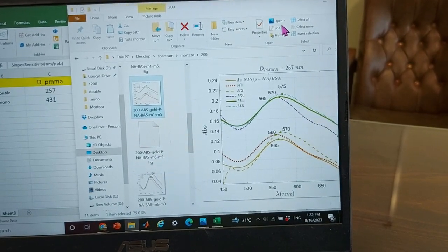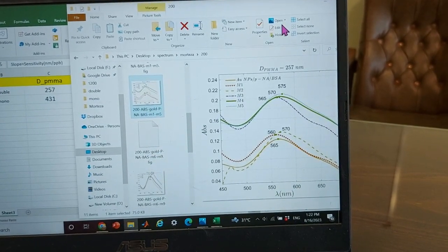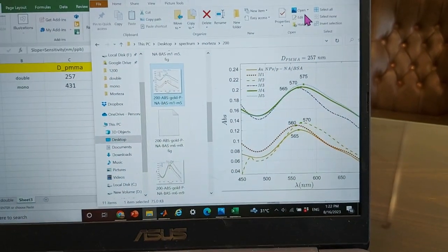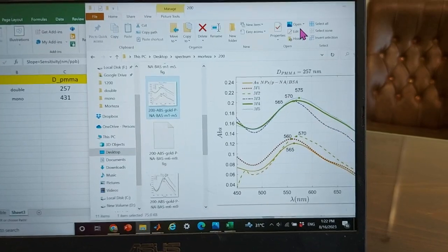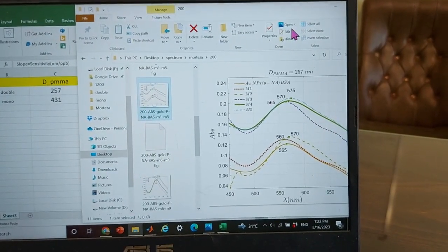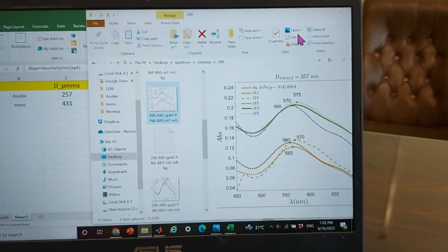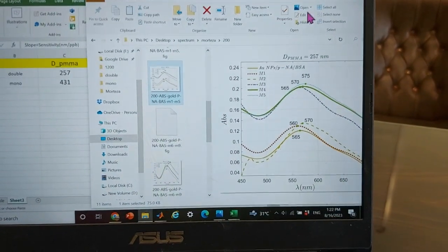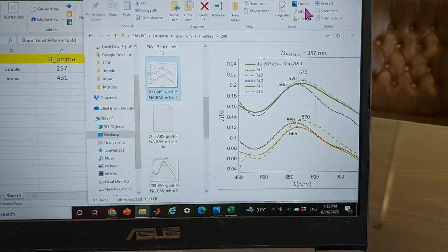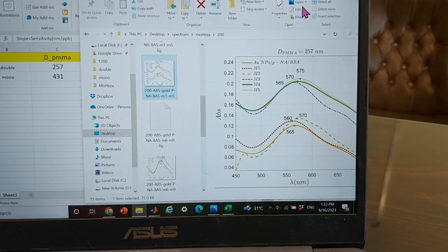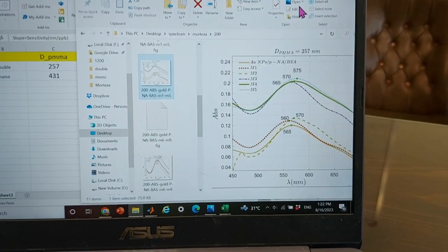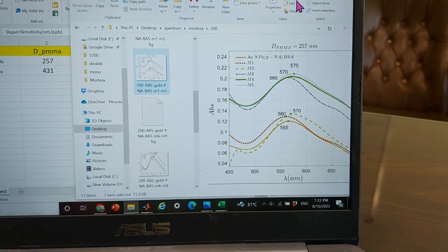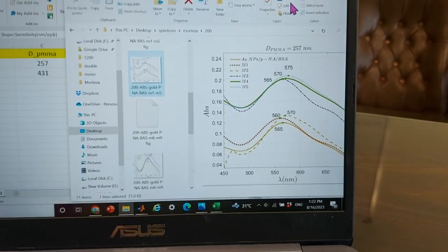But in one layer, you have nanoparticles that are near to each other. So the conclusion of both of your works is saying something very important: whenever we want to fabricate a very highly sensitive LSPR sensor, we need to design samples where the distance between the nanoparticles is not so large.